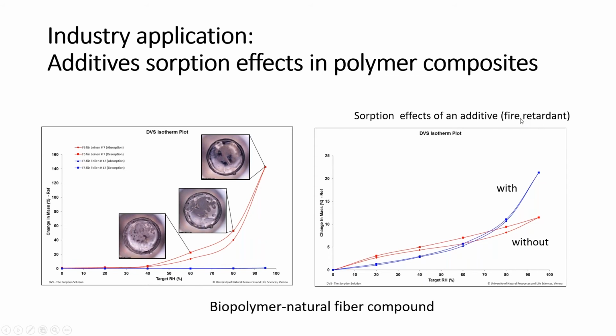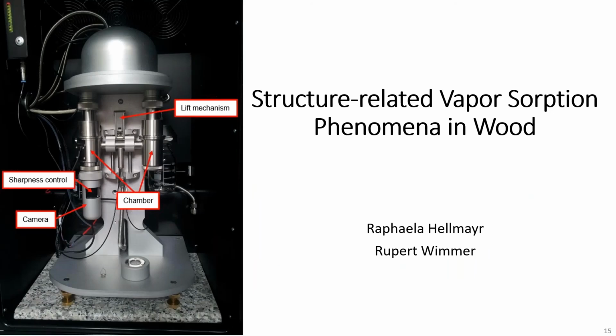Some specific treatment was necessary, and the question: how is the sorption behavior? And Raphaela has done all this analysis. How is it when you do sorption with and without that agent? And it showed, when you look at the right picture, with and without, there was a big, huge change. There was also a phase change that we picked up, but especially this fire retardant had a strong sorption behavior, and it changed the chemistry of it, and that was important information to know.